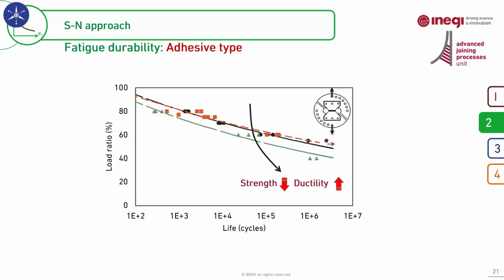In another study, we analyzed the effect of adhesive type. We tested joints with different types of adhesives from different families, with very different static strengths and very different mechanical behavior under quasi-static loading conditions. As a general trend, you know that the lower strength adhesives tend to show a shorter fatigue life, but when we plot results against load ratio, which is defined as the fatigue load divided by the respective static strength under the same loading condition, we see that there is no big difference like the one we usually observe in the static results for SN curves. It means that even without performing experiments, we are able to have a very rough idea about the fatigue life if we know the load ratio.